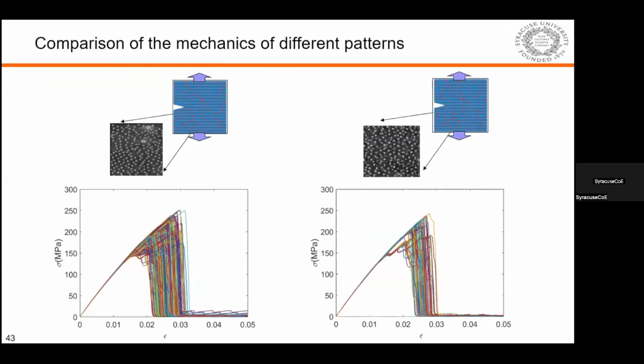And then we use those generated conformations as the input to do a mechanical test. We assign the particles the mechanics of silica, and the matrix the mechanics of cellulose, and then we do a lot of tensile tests on both the original SEM picture and those generated images. And we show that they have very similar strength, toughness and stiffness. That means the generative AI images are not only visually similar, but might also capture some orderliness in the particle distribution.